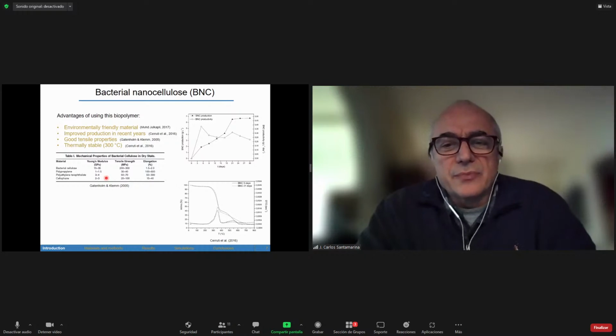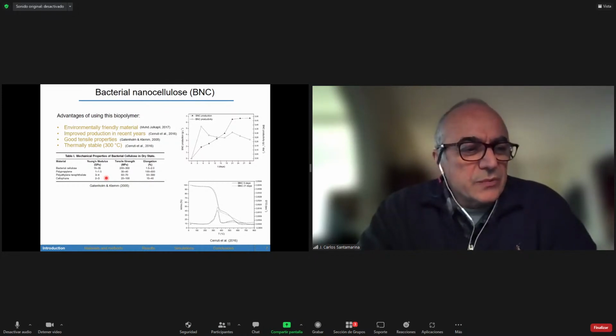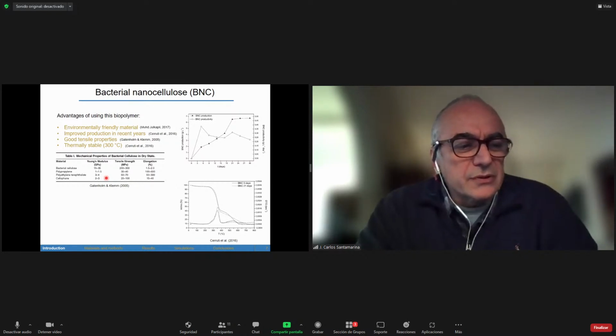Now, I did some brief computations of how much water can be absorbed onto these nanofibers. Assuming that you have 100 meters squared per gram, and I give it a full nanometer of water, that means 4 monolayers of water, etc., which is probably not realistic. Probably the amount of water would be 10 to the minus 4 with respect to the amount of cement. Your water cement ratio is 0.44, so this would be minuscule.